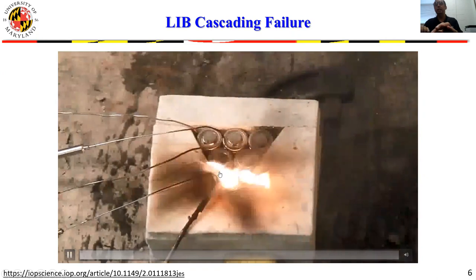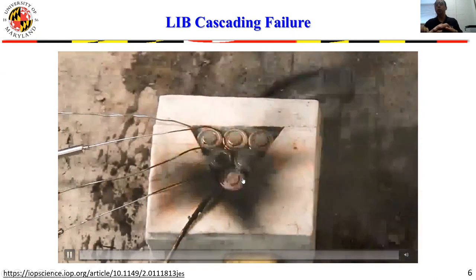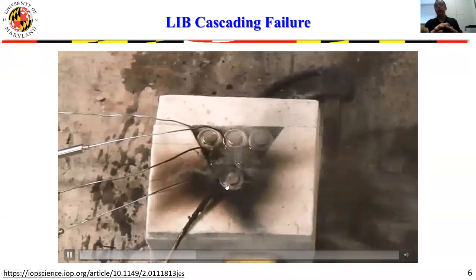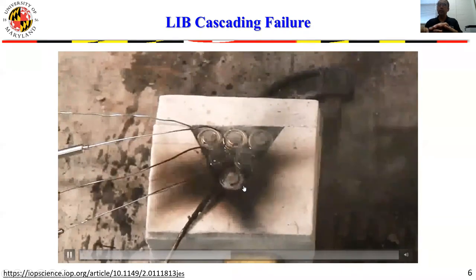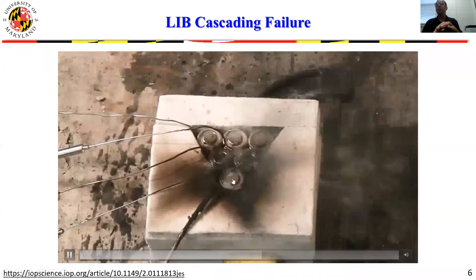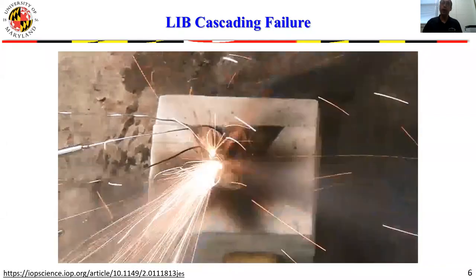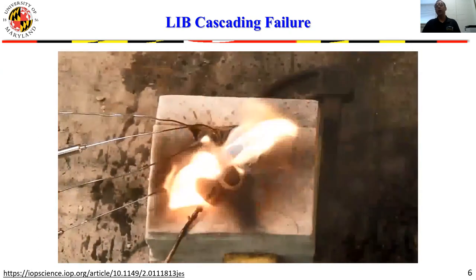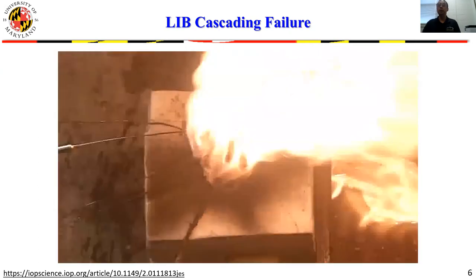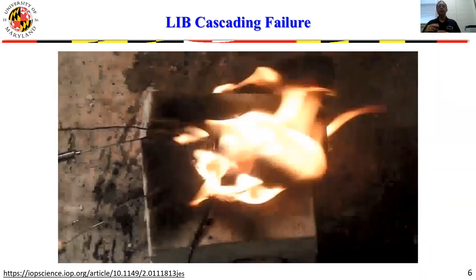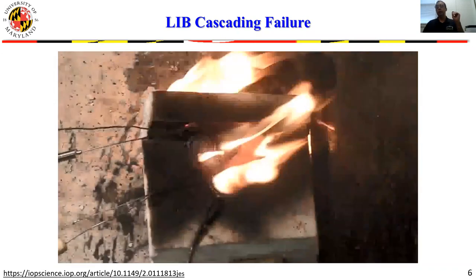So in this particular experiment, we forced this bottom corner cell into a thermal runaway, and we're looking at what happens to surrounding cells. You can see the surrounding cells start to vent, and that's because, of course, they're being heated by the cell that was forced into thermal runaway. And this time, they start to fail as well, one by one, and that failure in this particular case quickly accelerates into a full-blown fire. Now, the example that you see in front of you is six cells. Just to give you a perspective, a modern car battery pack can contain up to 6,000 of those cells. So we're talking about a 1,000 times larger fire size.